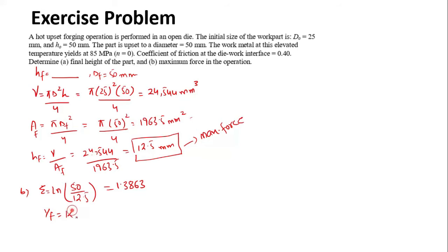We have the flow curve equals K into the strain to the exponent n, the strain hardening exponent. As it's a hot forging, we know that the flow curve would be equal to the yield strength of the material. In this case, we have a yield strength of 85 megapascal. So we'll simply write 85 into 1.3863 to the exponent of the strain hardening, that is equal to 0. So we have flow stress equal to the yield point, that is equal to 85 megapascal.